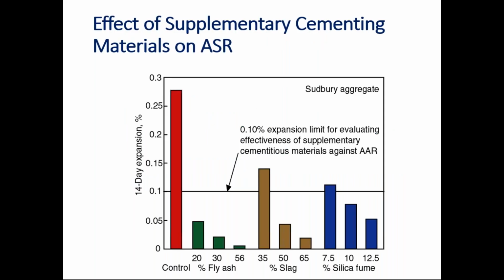So these are some of the effects of supplementary cementing materials on ASR. You can really reduce it as you use the fly ash, as this percentage of slag and silica fume. So the expansion goes below the broad line, 0.1% is the expansion value. So when you use all these other things, you can see that the expansion reduces due to alkali silica reaction.